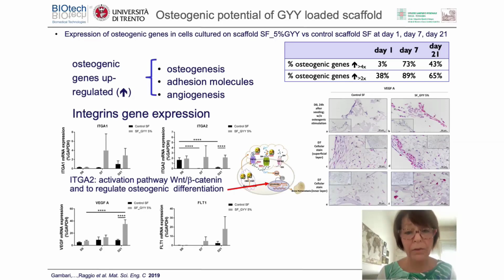So in 12 hours, the system was able to be reactivated, and then the cells start to do the job without the need for the release of more molecules. So this is a good example of how we can reduce drugs, how we can reduce the release time, which is very beneficial for cost and for time, even because we don't need to keep the molecules active for a long time. But what is needed is to precisely identify the mechanism we want to reactivate, a biomimetic approach, and then to release just for the time needed to reactivate the mechanism. And this is a kind of sustainability.